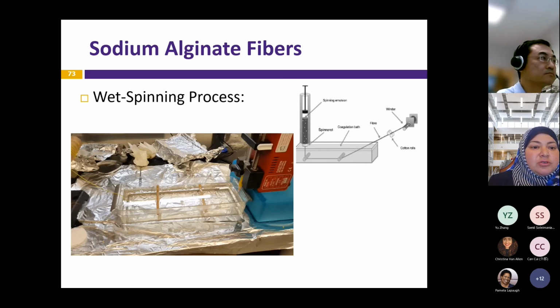So it uses, as you saw, a wet spinning process. The core material was, in that case, a green bioproduct, which is the same one I talked about a minute ago, Rejuve 8. And the bath right here is just a calcium chloride bath at a molarity of 0.6. And as you can see, the fibers are formed and then they are left to dry before we cut them and put them in the binder.